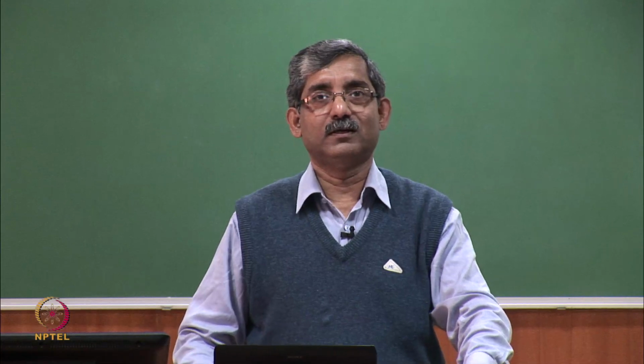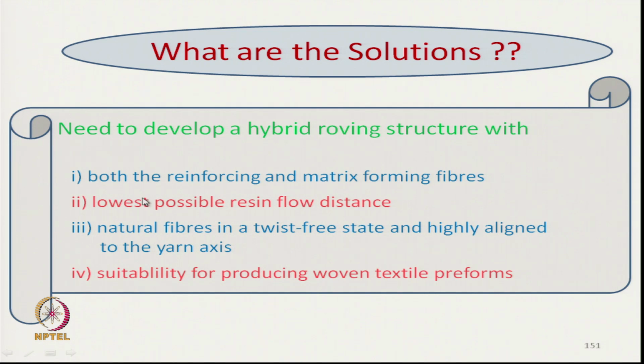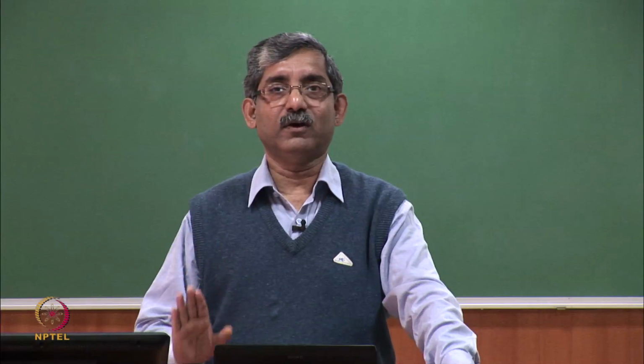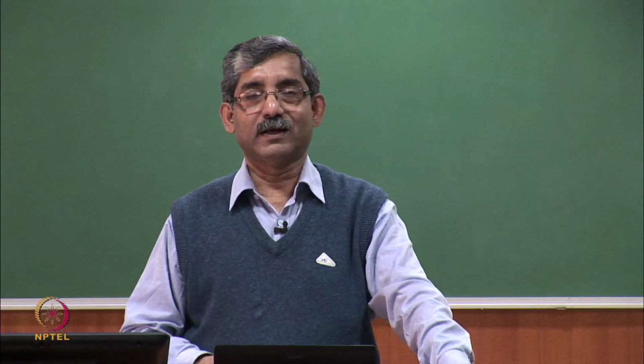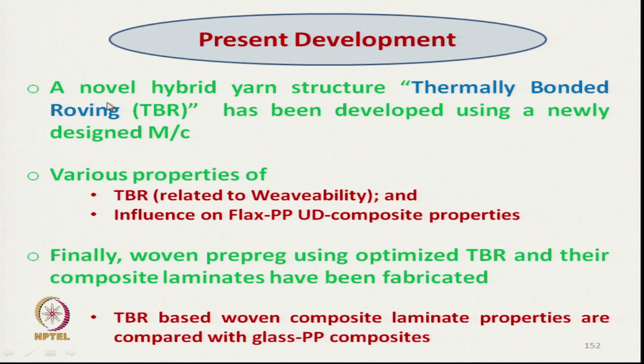So, the main solution here is that both the reinforcing and matrix forming fibers should be there in the hybrid roving structure to have the lowest possible resin flow distance. The natural fibers in the twist free state are highly aligned to the axis of the roving, and we have to develop the yarn or roving structure in such a fashion that they are suitable for weaving to make textile preforms. This novel structure we call thermally bonded roving, TBR,